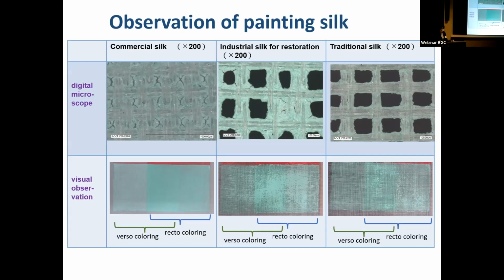In the images you see here, the left one shows modern painting silk. The central one shows modern silk used for infill treatment. And the right one shows a traditional type of silk woven in the same structure as the central one. The surface of the sample using modern painting silk is filled with pigment, which can be attributed to the tightly woven structure of the cloth. This type of silk is woven too tightly to see pigment on the backside from the front, which is suggested as one of the main reasons why pigment is rarely applied from the backside these days.